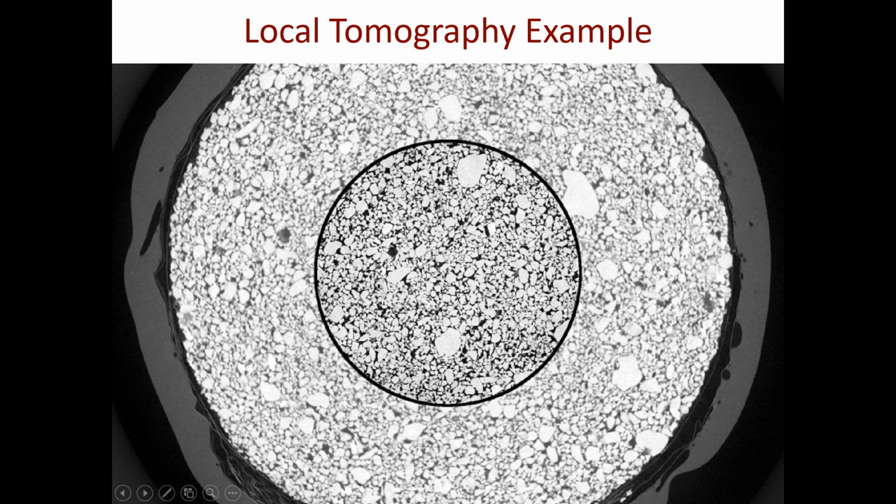So that can be a problem, but then you have to understand if you have the outside that you're trying to image through, that is essentially often filtering your polychromatic beam, and you have to know that during the reconstruction in order to get better images. So more often than not, it's better to have things cut to the size you're wishing to actually image. And that can change depending on the application. Okay.